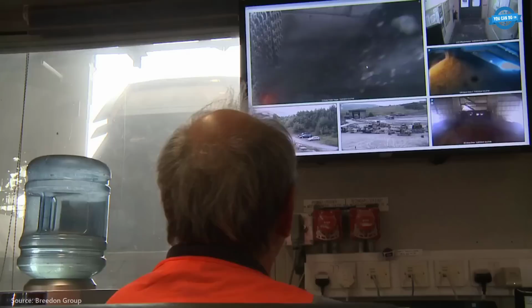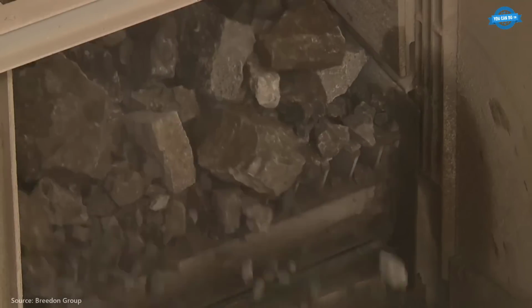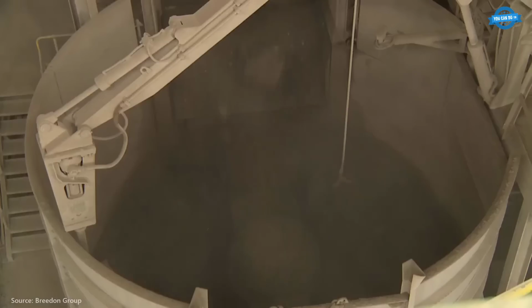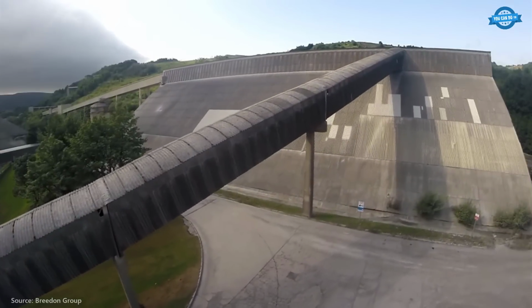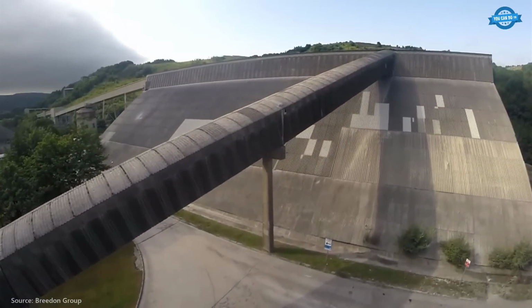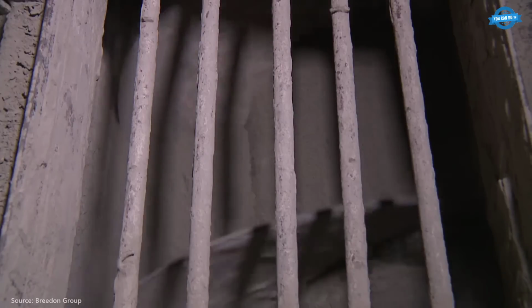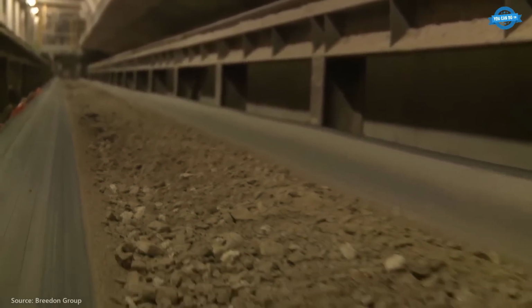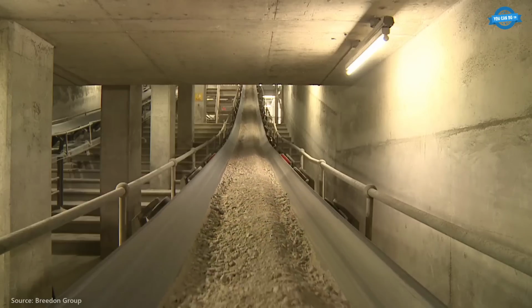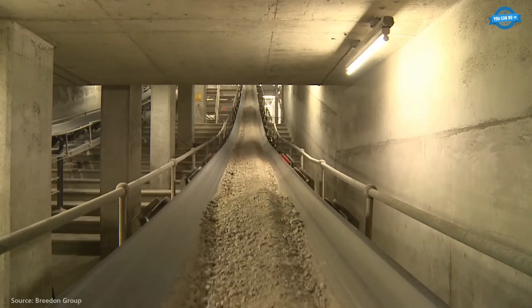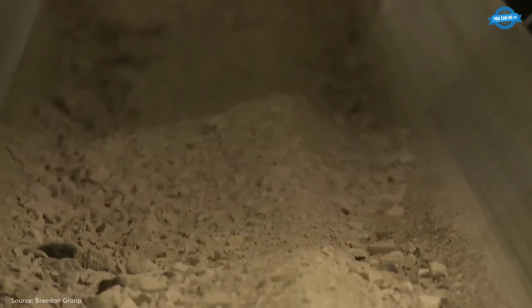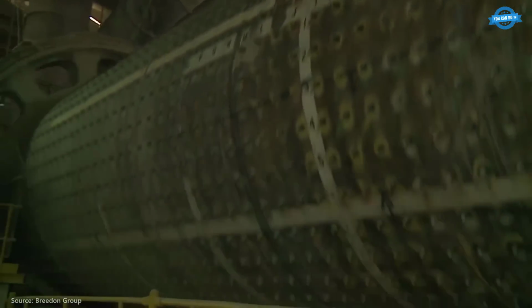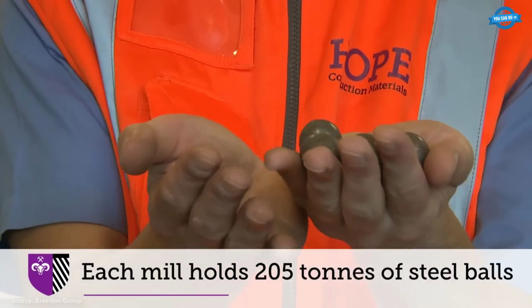Once crushed, the limestone and shale are transported to mills where 205 tons of steel balls grind the materials into fine powder. Pulverized fly ash, PFA, a byproduct from coal-fired power stations, is also used as a partial replacement for shale. The resulting raw meal is transferred to a blending silo and then sent to a preheater tower where it is heated from 80 degrees Celsius to 830 degrees Celsius.